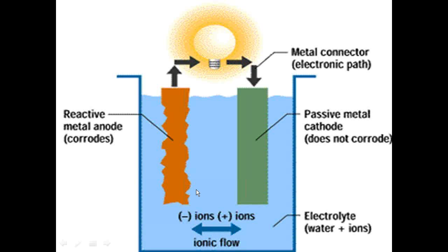There's a battery, which is actually a corrosion cell. We've got the anode, which corrodes. We've got the cathode, which does not corrode, that the anode is protecting. They're connected through a metallic pathway, and we've got the electrolyte. Now that light bulb is part of the metallic pathway. If you shut the switch off and shut the bulb off, or if you took it out of the socket, you would no longer have the 4 components, because that metallic pathway would no longer be continuous.